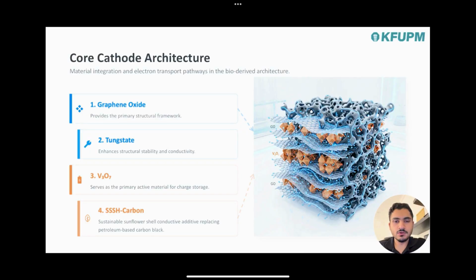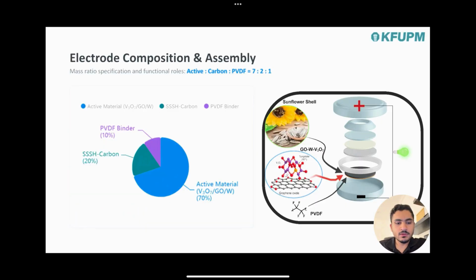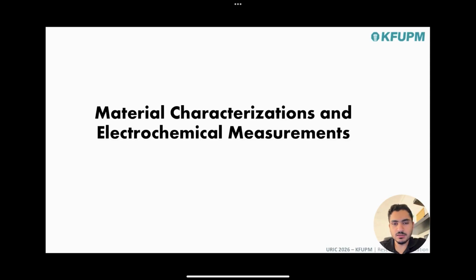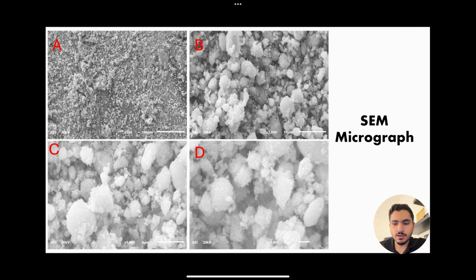Thank you, Muhammad. To test our idea, we designed the cathode with specific material characteristics. Our core cathode architecture is composed of graphene oxide sheets in addition to tungstate intercalated in vanadium oxide, in addition to sunflower shell carbon. The mass ratio of our electrode composition is 70% active material, 20% sunflower shell, and 10% PVDF binder. On the right side of the slide, we have an explanation of how the entire battery was assembled. Let's move to the material characterizations and electrochemical measurements, starting with the SEM micrograph, where we have 4 different magnifications between 100 micrometers and 1 micrometer.